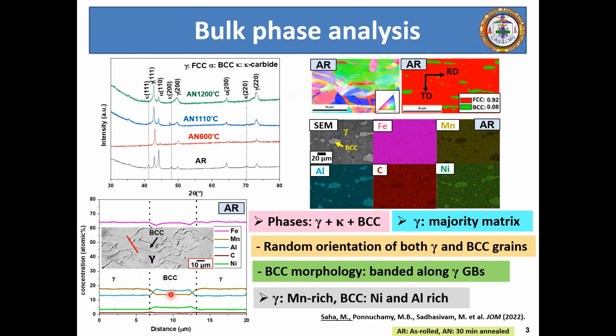So now the interesting question is, we have already seen the presence of peaks corresponding to the kappa phase in the XRD patterns, but from none of the SEM-based microstructure investigations do we see the presence of the kappa phase at all. This means that we need to have a better understanding of the chemical partitioning information in the gamma and the BCC phases separately. So, for that, we have embarked upon the site-specific 3D APT analysis, initially in the as-rolled condition.